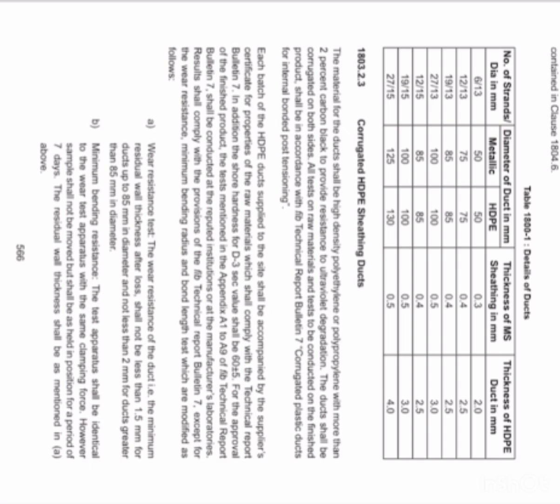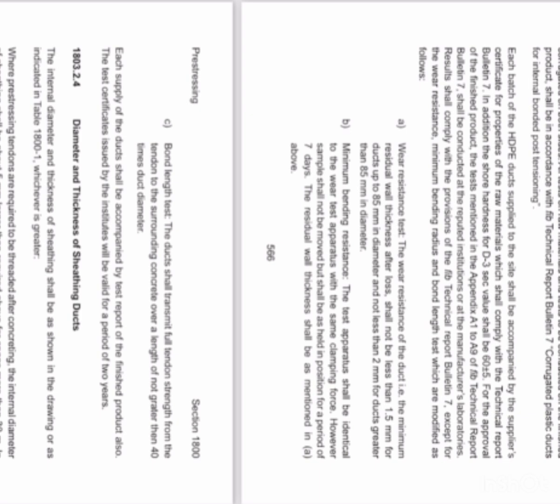Wear resistance test: The wear resistance of the duct, that is, the minimum residual wall thickness after loss, shall not be less than 1.5 mm for ducts up to 85 mm in diameter and not less than 2 mm for ducts greater than 85 mm in diameter. Minimum bending radius: The test apparatus shall be identical to the wear test apparatus with the same clamping force. However, the sample shall not be moved but shall be held in position for a period of 7 days. The residual wall thickness shall be as mentioned above.